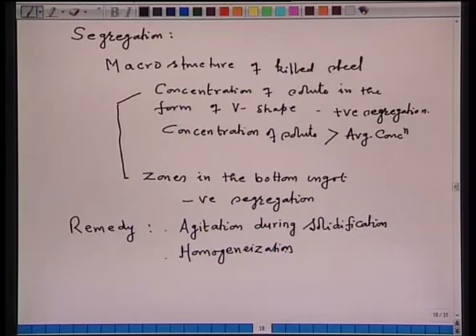This homogenization treatment is given after solidification to the ingot during the reheating stage. Homogenization does not form a part of the solidification process, but forms a part during rolling or heat treatment operations. At that stage, the microsegregation in killed steel ingots can be eliminated by homogenization — that is, by heating over a long period of time.